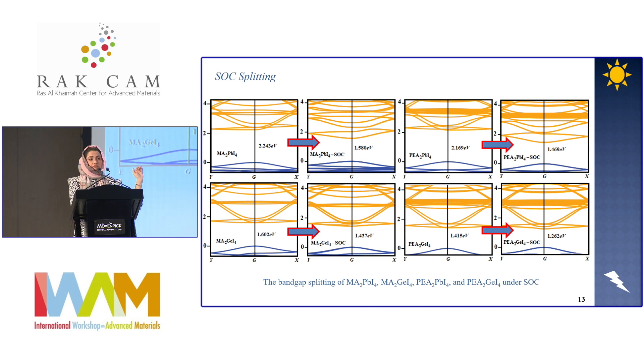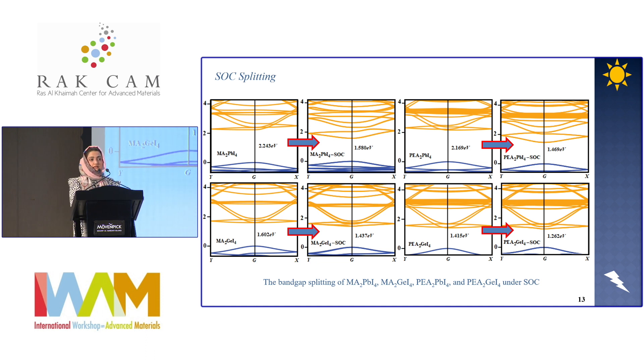I also studied the SOC (spin-orbit coupling) effect. In this case, the band gap is further reduced because spin-orbit coupling splits the conduction band across the gamma point, and we can clearly see the further reduction in band gap. This SOC effect is most prominently pronounced in the lead case, because lead is a heavy element and more active toward spin-orbit coupling compared to germanium, where comparatively less splitting at the conduction band is observed.